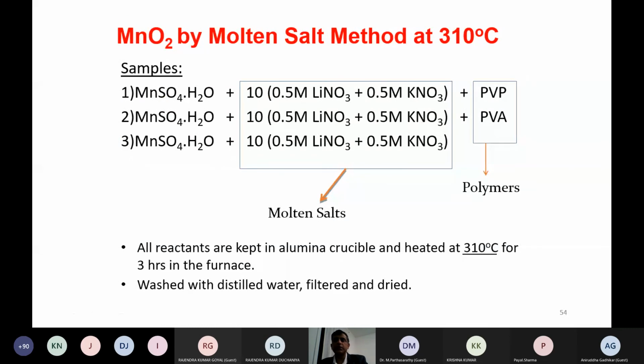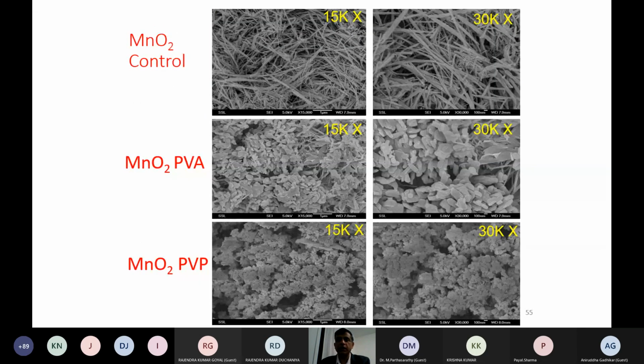Another example is MnO2. Usually people use a hydrothermal bomb, but the best way is to use the same molten salt approach. You can use manganese sulfate, or sometimes a polymer precursor. Just see what is going to happen. Remember, a rod type of morphology we can get by using this approach, and using the polymer we can see the difference in the morphology.